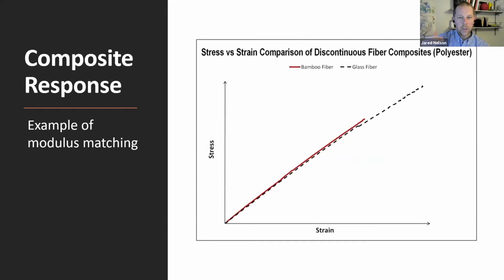So then, with that increased volume fraction, we can now start to see that as a composite material, we are starting to get really competitive. These two lines, between our bamboo fiber composite and our glass fiber composite, are nearly identical up to this point. The glass fiber is still going to be a little bit stronger, and it's still going to have a bit more deflection or deformation before it fails. But generally speaking, by substituting bamboo in, we've attained a close comparison and a similar material response.